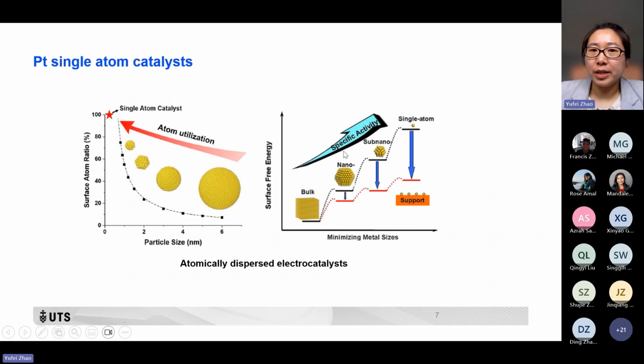Similarly, for the specific activity, we can see from the bulk to nano to sub-nano and to single atom, the specific activity also increases very fast. But the problem is the surface free energy. When we decrease the size of the nanoparticles, the surface free energy also increases correspondingly. This increase of the surface free energy will induce aggregation of the materials. That means the metal single atoms or atomic clusters may aggregate together to form nanoparticles or larger particles. So we need to find a suitable support to stabilize the metal single atoms and atomic clusters and maintain their atomically dispersed properties.